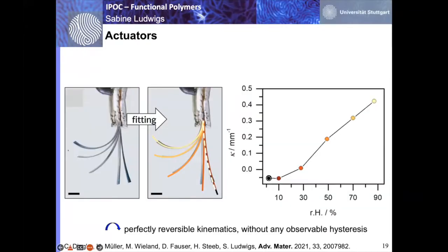So we built these actuators. In a first step, we just did fitting of the curvatures, which you see here. This is the curvature as function of the relative humidity, again, here from dry conditions to 90% wet conditions. We find reversible kinematics, and we don't observe any observable hysteresis, which is already good.